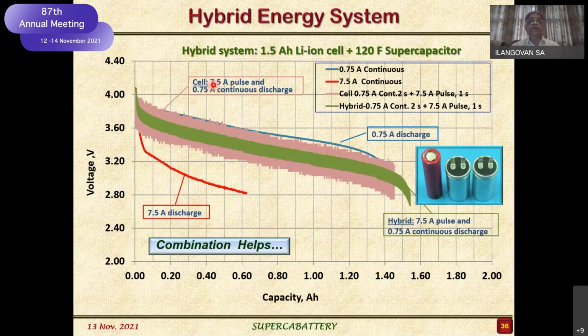See, all the applications do not involve a continuous discharge at a very high rate. It is an intermittent peak requirement that is to be met by the supercapacitor. It is instantaneously getting recharged. See, I am able to withdraw almost 80 to 90% of the energy available in the battery while maintaining a 7.5 ampere pulse, and the supercapacitor acts as the intermediate system to deliver the power. So it is kind of keeping the capacitor charged with energy and the battery is provided with peak power by the capacitor. So this is how we started.